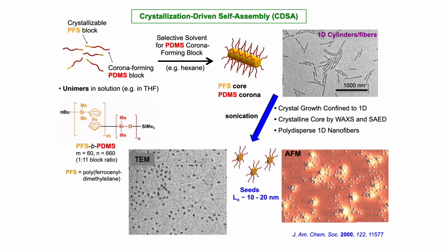So how do you do this? Well, the key is to take these structures here and sonicate them using an ultrasonicator, and you break them down into little seeds. So these are about 10 to 20 nanometers long, you can see here.